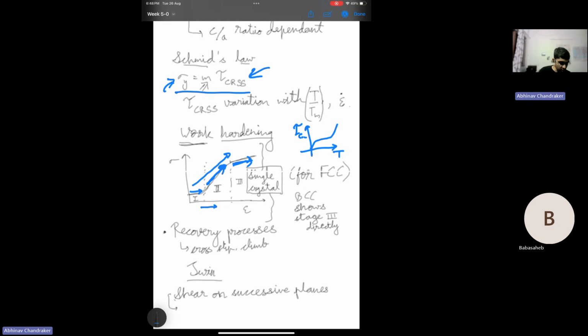After that, once you have sufficient density of dislocation, other recovery mechanisms will start to dominate. So one thing is that the stresses are so high that the dislocations will be able to move on different slip planes, which initially could not be activated due to lower stresses, but at higher stresses, their CRSS values are being reached, so they will also get activated. So mobility will improve.